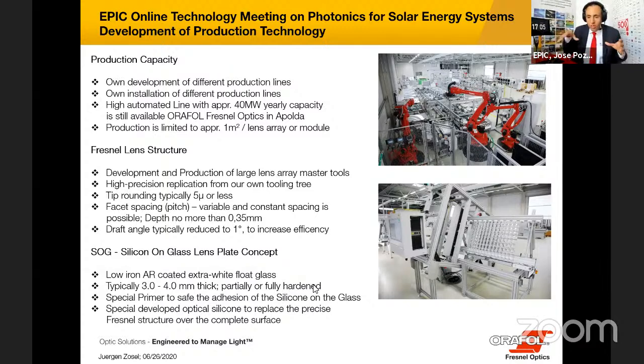And this AR coating, you develop yourself at ORAFOL? But we work together with the Fraunhofer Institute and a glass partner to have a special coating, which we could use over the full range. Okay, so basically, with collaboration, you can really enable almost any coating that can be deposited on top of Fresnel optics in the large volume, and the whole production is there.